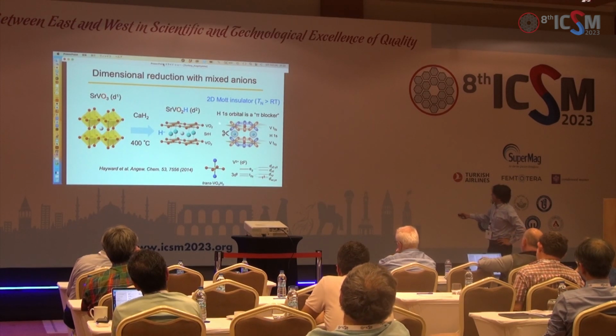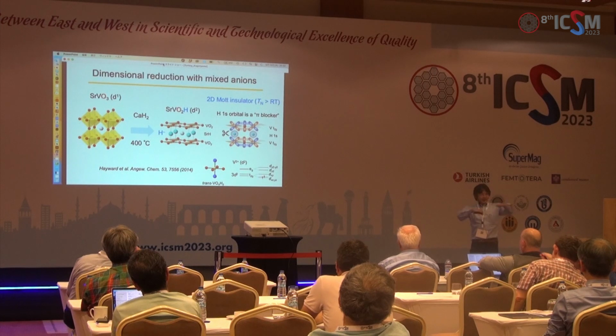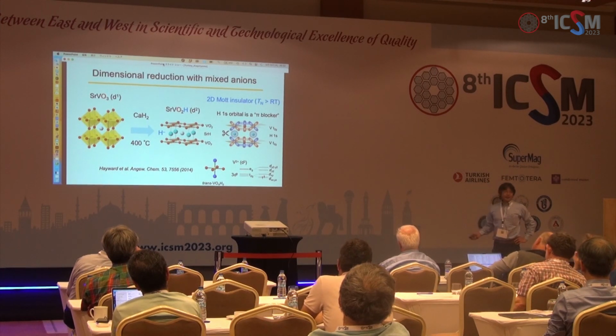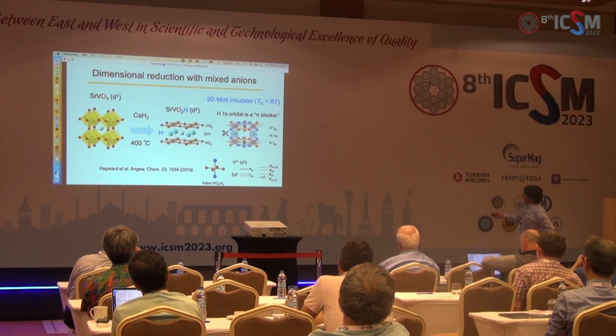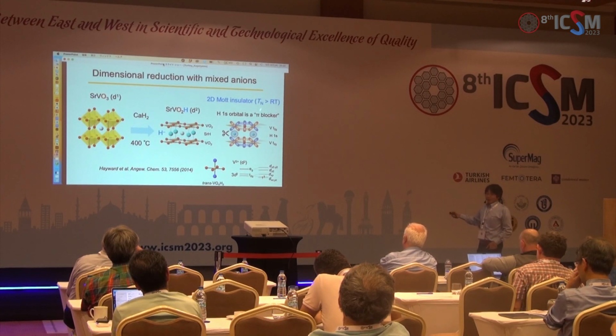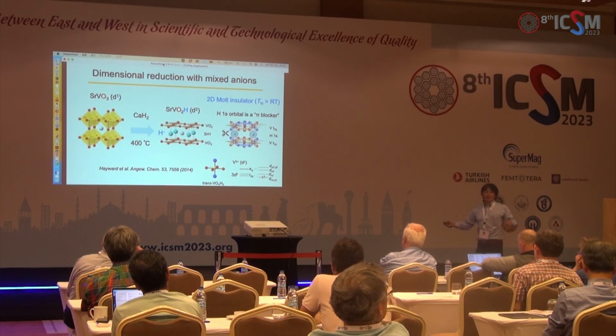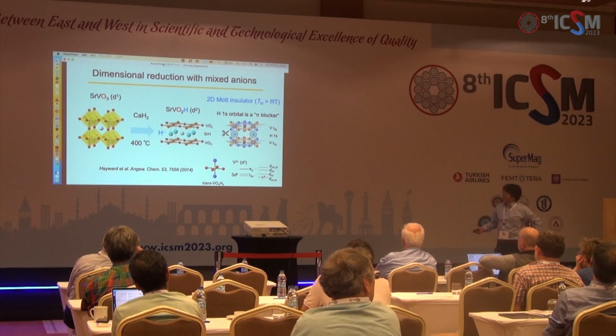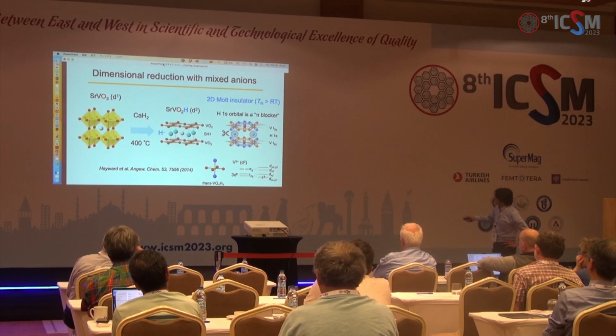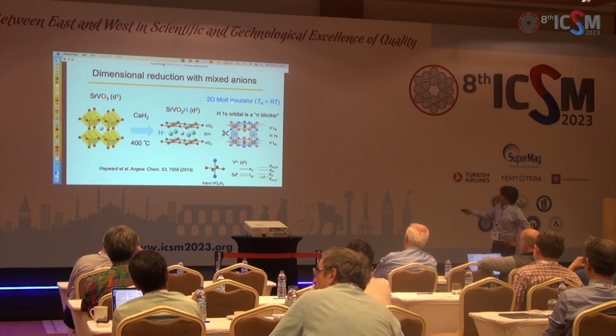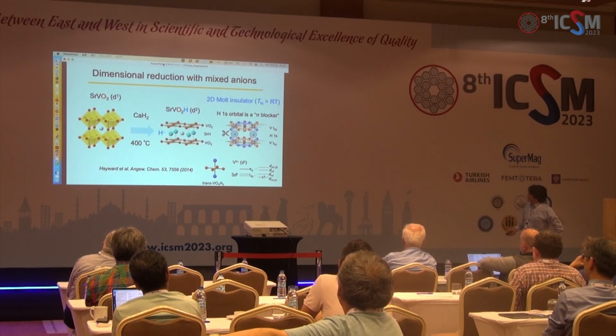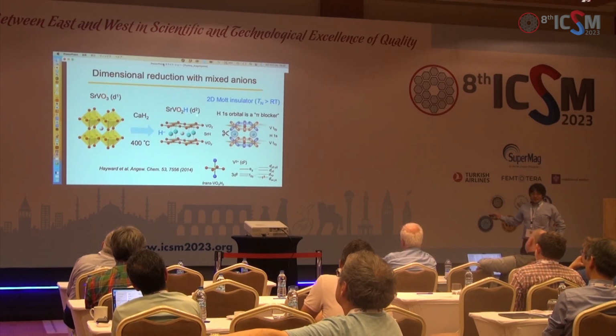So you may call this hydrogen 1s orbital a sigma symmetric orbital, which can be cut with this hydride ligand. So now we have a two-dimensional structure starting from the perovskite material, and from some magnetic measurements and so on, we know that this material in fact is a metal-to-insulator material. The starting material is a paramagnetic metal, so nothing interesting. But as a result of this reduction and this scheme, we actually have a very interesting situation where the 2D insulating state is realized. In fact, this material stays insulating at least at room temperature, so it is very interesting.